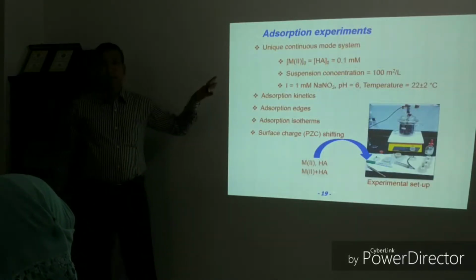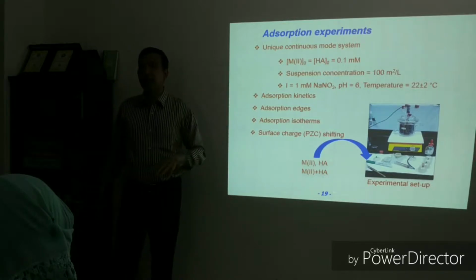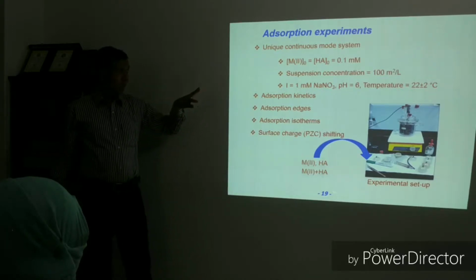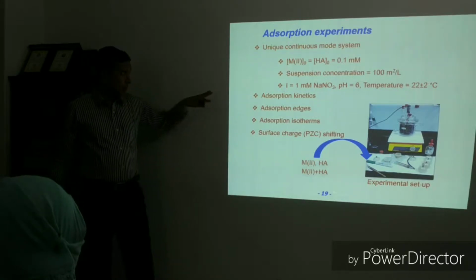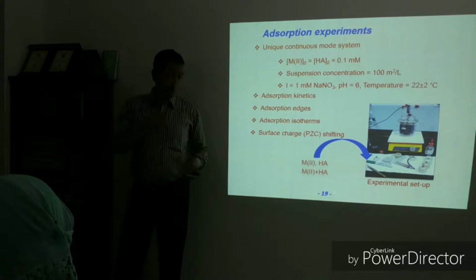Then we have performed adsorption experiments. This is a very unique experimental system. It is known as a continuous mode experiment system, in which the suspension was in the reaction vessel. Here we have shown the reaction vessel for the entire period of experiments, and these are the experimental conditions. We have studied adsorption kinetics, adsorption edges, adsorption isotherms, and surface charge shifting to understand what actually happens when various pollutants adsorb onto the surface.